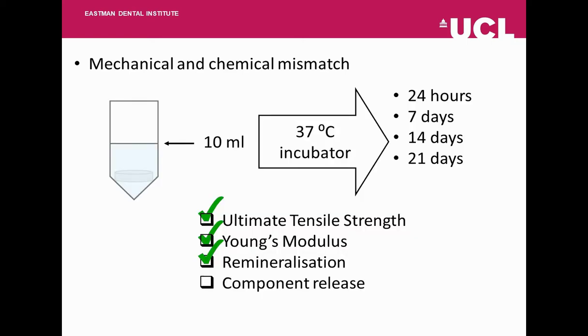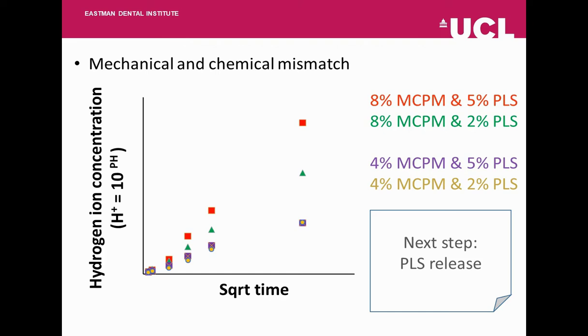Finally, looking at component release. This is important during remineralization because we don't want completely acidic conditions, especially when our composites will be in an environment where cells are to be recruited for healing. This is a graph looking at the release of hydrogen ions versus square root of time. And the graph shows us that with increasing levels of monocalcium phosphate and polylysine combined, the material releases more hydrogen ions than the lower monocalcium phosphate and lower polylysine combinations.